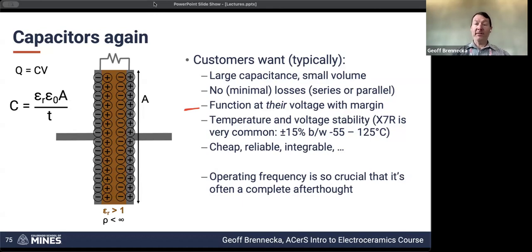Ideally, that's the highest possible capacitance, but many times the stability is far more important than whatever the maximum is at a given single temperature. And so because of this, the industry standards have come up with a variety of different classifications. The most common one for commercial application is X7R. That just says that the capacitance will not change by more than plus or minus 15% between -55 and 125 degrees C.